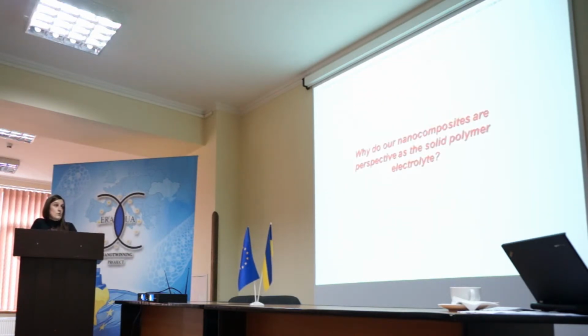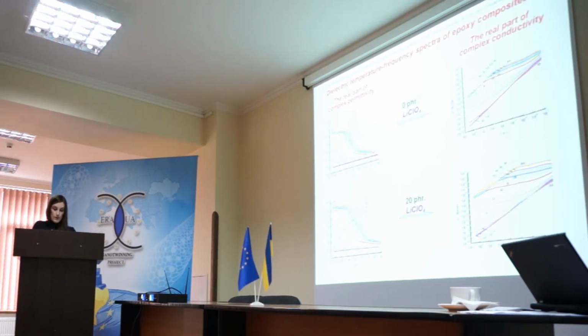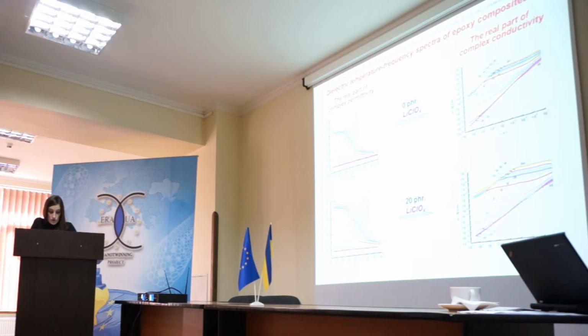We studied whether our nanocomposites are perspective as a solid polymer electrolyte. At temperatures below the glass transition temperature, permittivity has a low value and varies heavily with frequency, indicating the blocking effect of free charge, which occurs due to the low mobility of macromolecular chains of the polymer matrix. In the same temperature range, the values of the real part of the complex conductivity vary linearly with frequency. The system is an insulator.